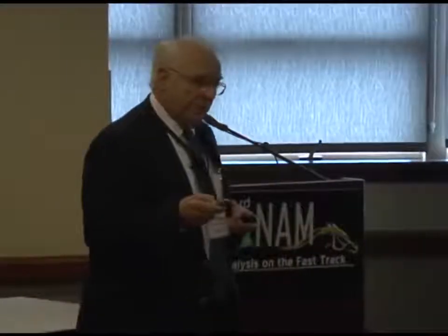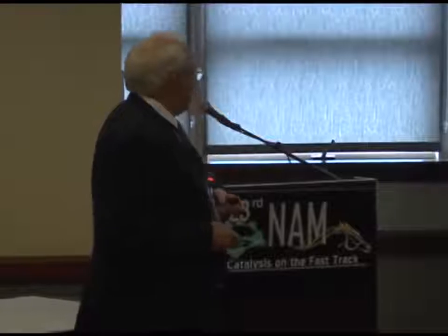And we choose amounts of metal, 1% typically metal on the sample, so that we have a sparse distribution. We're trying to get one person, one vote. We're trying to get site-isolated species. And I'll show you images that show that we can do that. So I'm going to talk mostly about rhodium and iridium.